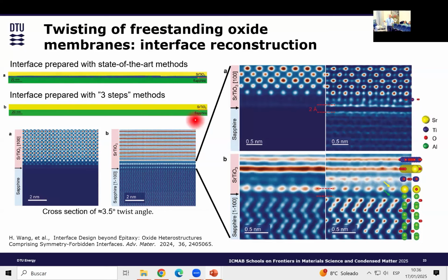So remember, this is strontium titanate on sapphire. Sapphire is the substrate, and strontium titanate is the layer on top of it. What they also observed, and I don't have a lot of time to go into too much detail here, is about 2 angstrom space, or a gap, between the two layers. A detailed analysis showed that the atoms on the surface of the bottom layer are aluminum, and they see the strontium on the top, but they are a little bit shifted. From their analysis, there is a slight distortion of the strontium towards the aluminum. And in the paper, they say that it can cause, for example, chirality or strain distribution at the interface.